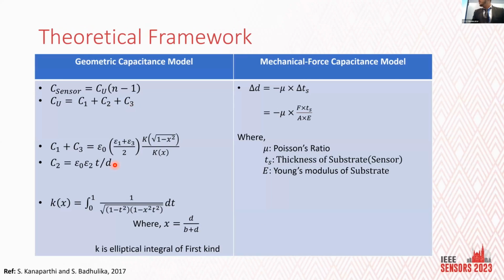I'll not go into detail with these equations. I referred to them from the literature, and these are for the capacitive sensors, which can be easily found using the elliptical integral of the first kind, which is very well known. And this is a simple mechanical model which takes into account Poisson's ratio, the Young's modulus of elasticity, and the force. So this D from this equation, which is the gap between the interdigits, is going to change with force. So if we apply force, the capacitance is going to change accordingly. And these are some parameters which can affect the interdigital structure, where N is the number of fingers which we have, and so on.